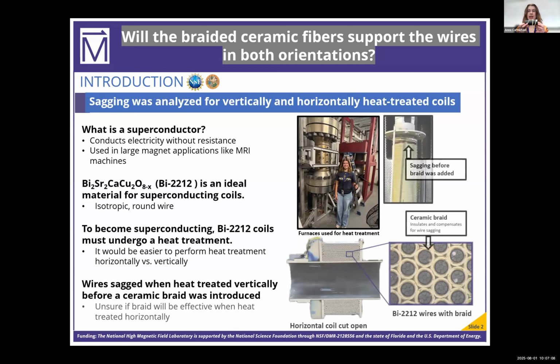The only downside is, like silly putty, these wires are extremely soft, so gravity causes them to sag downwards, which significantly decreases the performance of these coils. To compensate for this, a ceramic braid was added around the wires to help support it during heat treatment. This appeared to be successful when done in the vertical position. However, it was never quantitatively confirmed, nor was it tested in the horizontal position.